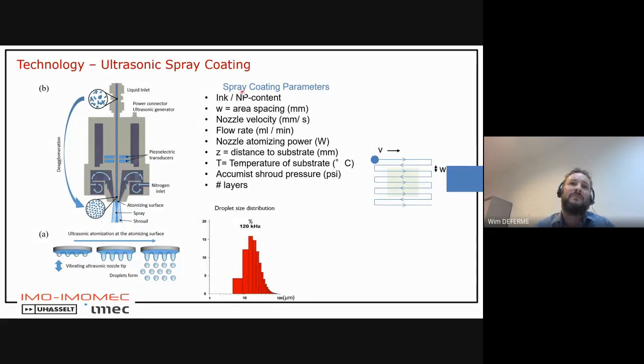So if you bring the droplet from the nozzle plate towards the substrate, there's a lot of parameters we can play with. Of course, in generating the droplets, you have the ink itself, the nanoparticle content, the polymer content, your concentration. But you also have, what you see here, the spacing of the deposition pattern. You have the velocity of the nozzle, so we move our nozzle over the substrate with a specific velocity. You also have the flow rate, so the amount of material you deposit per minute. We have the nozzle atomizing power, so the power you apply for generating these droplets. You have the distance to the substrate, so the distance between the nozzle plate and the substrate itself.